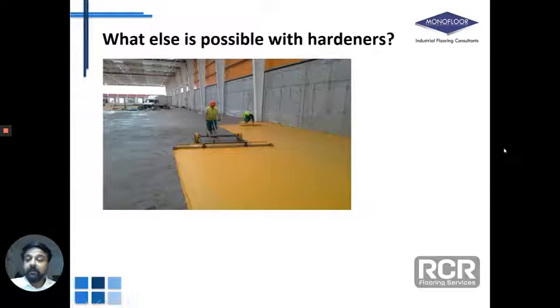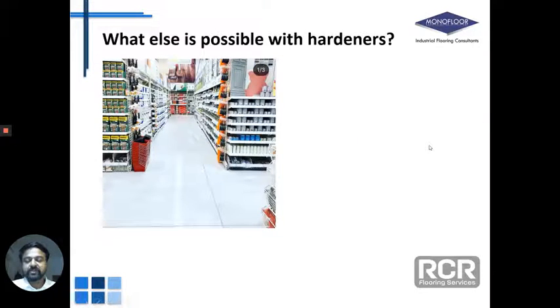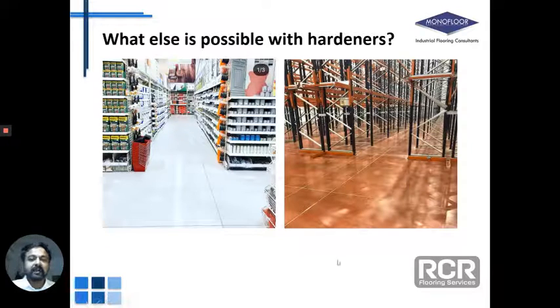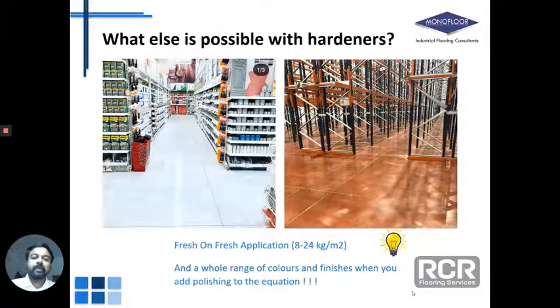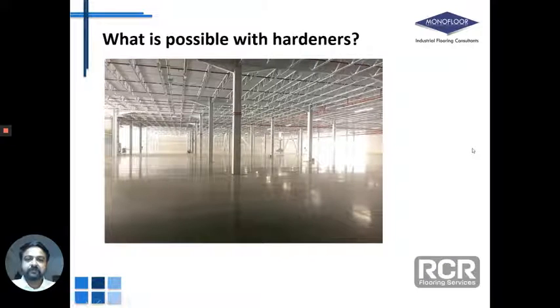By doing a fresh on fresh method, for example, you can obtain even, uniform colors on the hardener surface. So now, sky's the limit. You can choose any color that you like. You can use a fresh on fresh application to dose a really thick layer, and hence a much more consistent color can be achieved. And add polishing to it. You can imagine anything that you want to do with a hardener, and you can get really attractive aesthetic performance from these hardeners. So this is just to give you an example of what is possible with hardener.